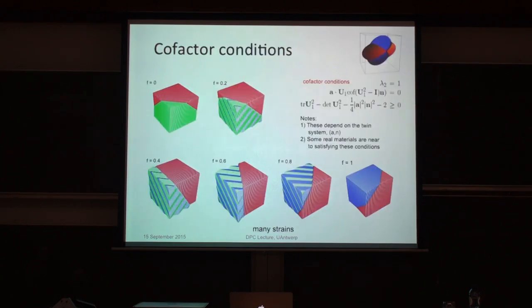So as I say, there's a degeneracy in this theory that describes this interface. And the degeneracy occurs when these mathematical conditions are satisfied. So first, you have to satisfy lambda 2 equals 1. And then you have to satisfy a second condition. Again, it's just geometry. It's a condition on the lattice parameters of the material. You have to satisfy an inequality. And these conditions are called the cofactor conditions. So this is quite recent.